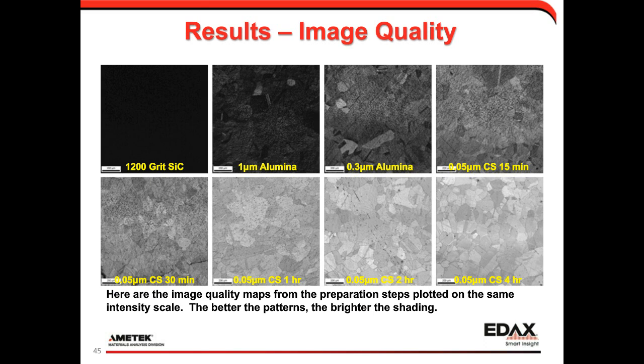So the method that's often used is to use what's called the EBSD image quality result, or IQ result, which is just a measure of the brightness and sharpness of the diffraction bands detected with the Hough transform. So if we plot the image quality map for each preparation step on the same scale, so the dark points here would have low image quality, the brightest points have the highest image quality. You'll see as we step through the preparation procedure, the image quality values improve. This is sort of what we'd expect. We're minimizing the deformation layer, we're improving the quality of the diffraction.